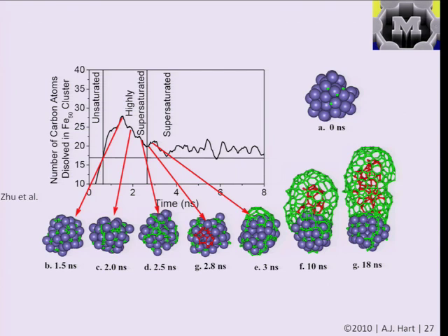And the same kind of idea that we had for growing nanoparticles in the gas phase, crossing a nucleation threshold to start to form the initial particles and then growing the particles, actually happens in an individual nanoparticle when something like a nanotube grows. Because when you start out with the particle on the substrate, before you've started to grow the nanotube, you have to saturate that particle with carbon, or in the case of a gold particle for growing a silicon nanowire, you have to saturate it with silicon and then cause a phase segregation, and then you can precipitate out the structure, and then the structure can proceed and grow.